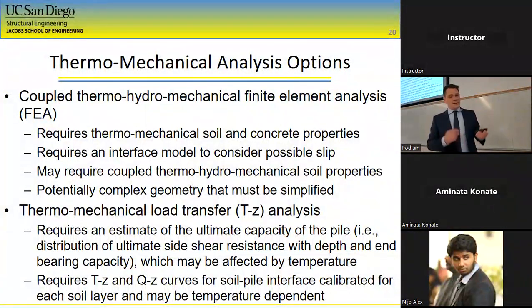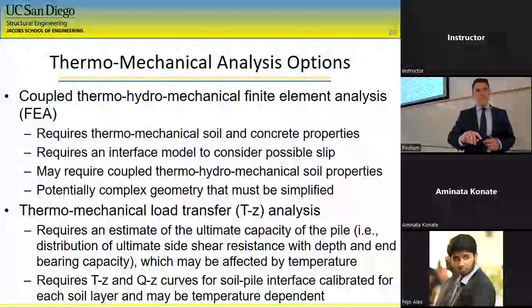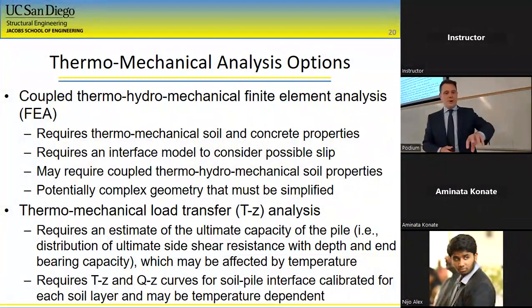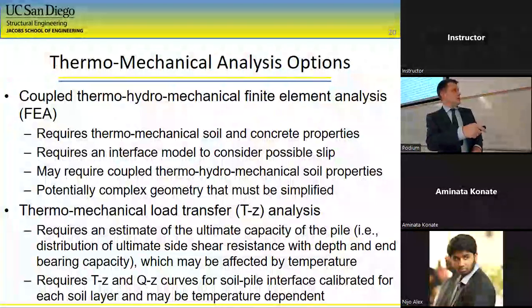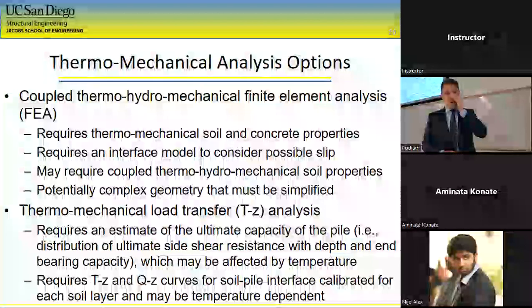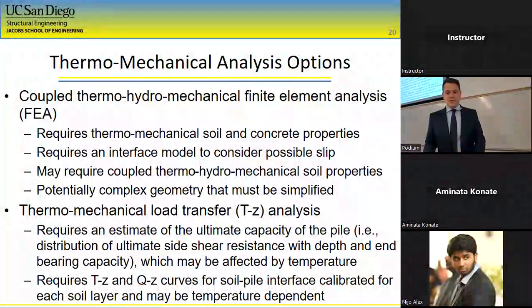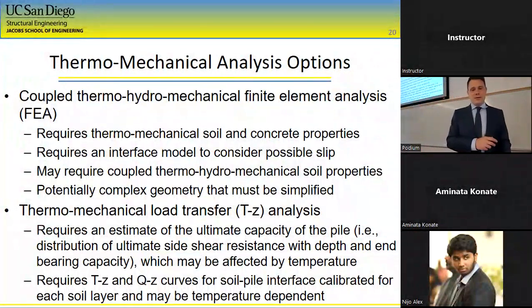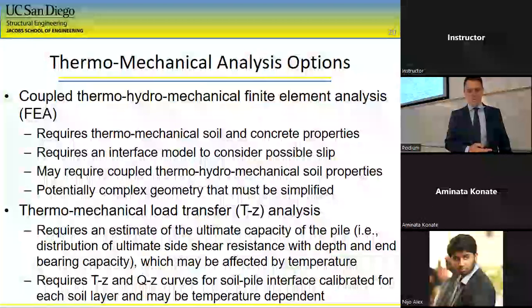So TZ analysis in this case is a very simple technique. You just need to have a representative stress strain curve for both side shear and end bearing. So we call those TZ and QZ curves. TZ analysis was developed at UT Austin by Lymon Reese and his colleagues, and Mike O'Neill here at Houston developed a lot of the empirical TZ and QZ curves that are used in practice.